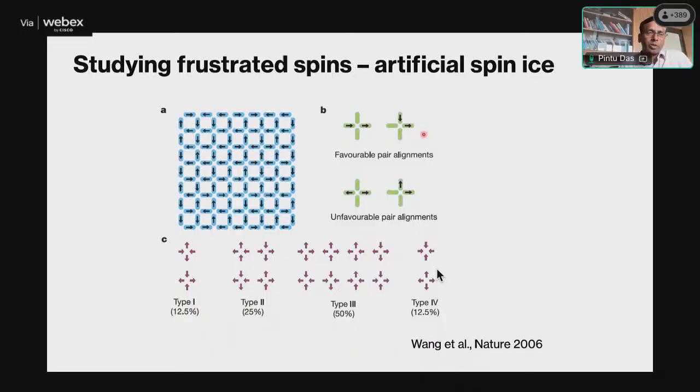That was the problem, because theoretically and also experimentally, people have not shown that there are skyrmions in those samples. They have just shown that these are transport signatures. Theoretically it is also not settled. It now turns out that there are a few different cases where very similar behavior can be observed, which may have nothing to do with any topology or topological texture in the underlying magnetic lattice. So therefore one has to be a little bit careful.